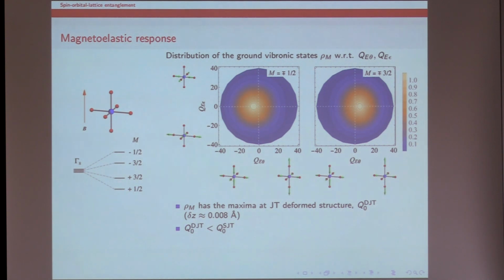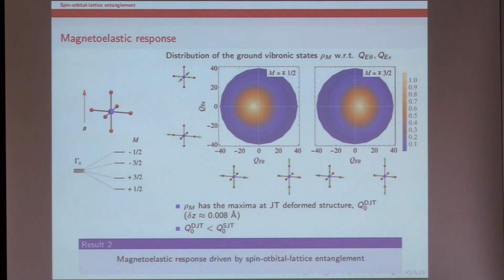What is the difference actually in this parameter? This is for this state. This is for the other state. And the deformation here shows the elongation is about 0.008 angstrom. And also, by considering the dynamical Jahn-Teller effect, we found the deformation here is smaller than the deformation showing the minima of potential. Smaller than the deformation of the minima of potential. So from here, this is our second result. Magneto-elastic response appears on site due to the spin orbital lattice entanglement.